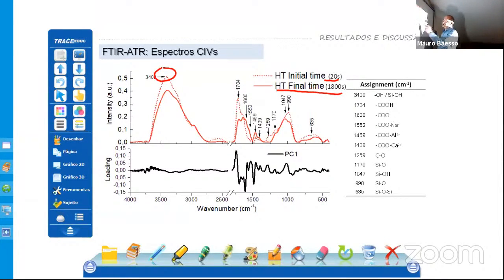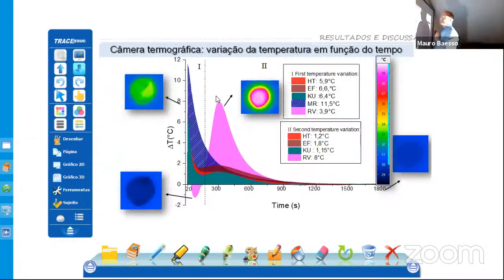After 1,800 seconds, you see the absorption bands, how they change a lot in intensity, and we monitor the change in the absorption bands, and then we got the image with the thermographic camera. It was very nice, because some cements, depending on their origin, have two stages. First, it heats up. In the first 20 seconds you cannot measure before that. It should be very fast.